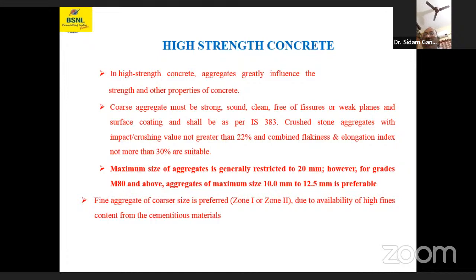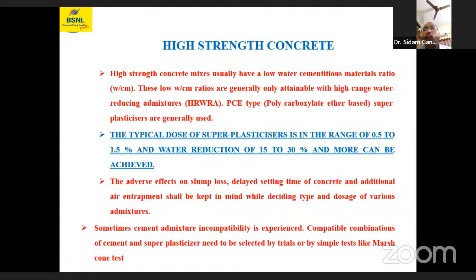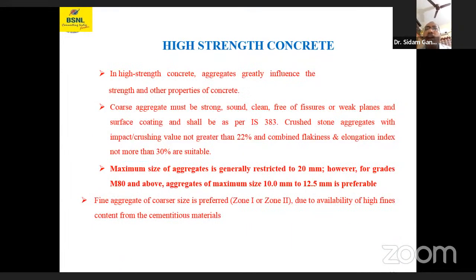Maximum size of the aggregate generally is restricted to 20 mm. However, for grades more than M80, aggregates of maximum size 10 mm to 12.5 mm are preferred. Why? Because for more than M80 grade, these are the only pumpable concretes. And fine aggregate of zone 1 or zone 2 is preferred due to availability of high fine contents from the cementitious materials.